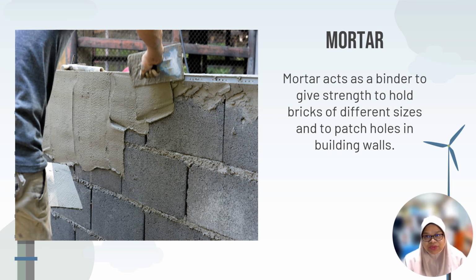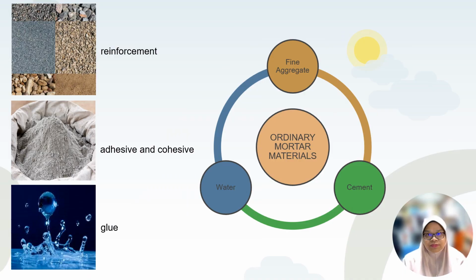Generally, for any brick strength, there is a suitable mortar strength that gives maximum strength to brickwork. The materials consist of fine aggregate, ordinary Portland cement, and water. First, fine aggregate. Aggregates are important in the construction industry because they act as a reinforcement to provide strength to the concrete. Approximately 60% to 80% of mortar or concrete is composed of aggregate.